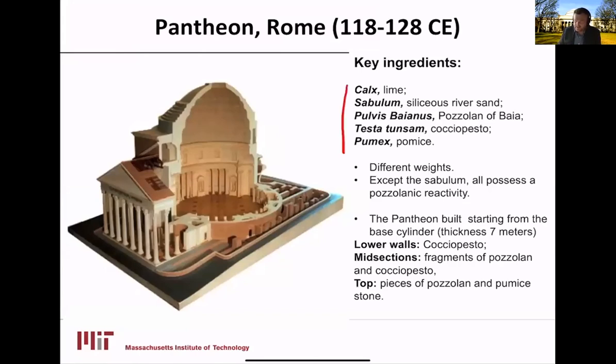So let me give you the recipe for the Pantheon. Indeed they used lime, sand, and pozzolan from Naples, Baia, coccio pesto, and pumice, and especially in the case of the Pantheon, the top part of this incredible dome, which measures something like 43 meters in diameter, with this oculus here, is made out of pumice mixed with pozzolans, because the pumice, we said, is very light, and because this is a huge concrete structure, it allowed these engineers to design something of such a dimension using concrete without collapsing.